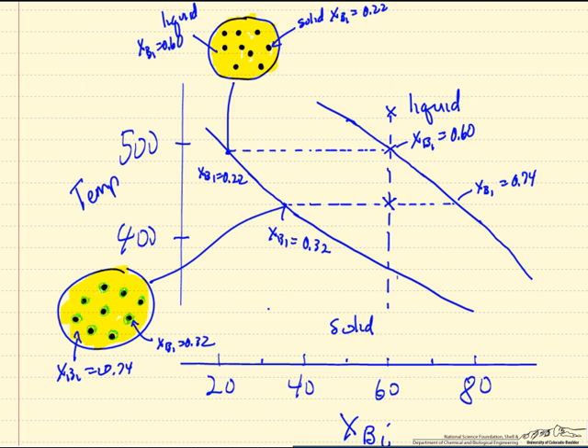In reality, as we continue to cool, it's a gradient and layered upon layered structure, so it's a continuous change. But it's a little easier just to represent it this way, and then we keep building more shells around as we cool further down.